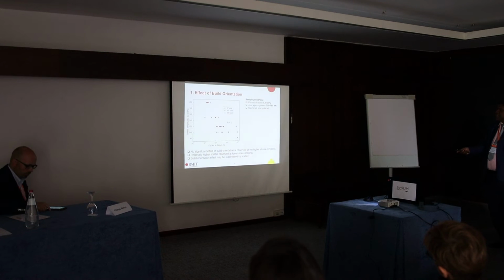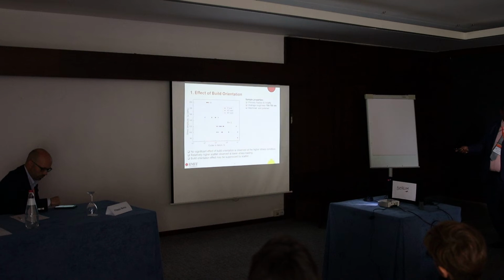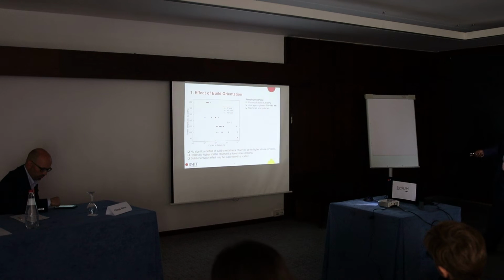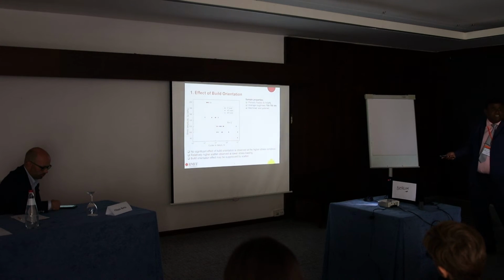So you can see at high stress, these fatigue flags are the same at a high stress amplitude with no effect of build orientation. At a lower stress amplitude, you get a large scatter. This is completely reversed cycle, tension-compression loading. Large scatter we observe at a lower stress. Build orientation, we believe in this case, may be suppressed by the scatter present in the data.